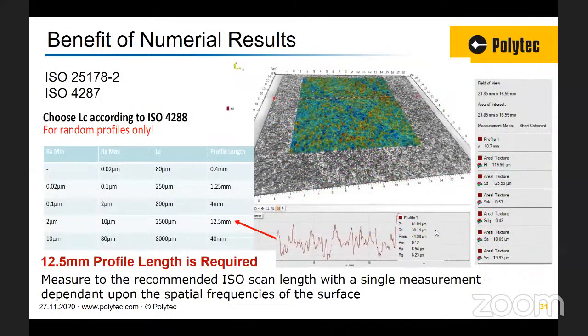And of course, ISO do give us some guidelines. You can always deviate from these guidelines if you so wish, but you should say so in advance. If we take the minimum Ra, it gives us a guideline at 2 microns and a maximum at 10 microns. That profile length should be 12.5 millimeters in size. Of course, to achieve that with any type of microscope system, you have to image stitch, and this takes time, and it can take much time. Whereas a macroscope system will clearly measure the whole surface within one single measurement, and measurements are very fast, concise, and repeatable.